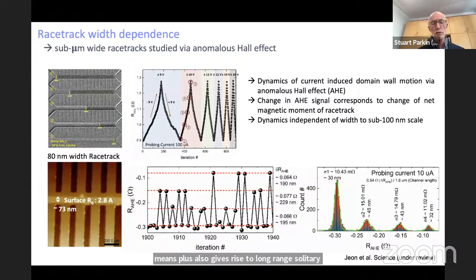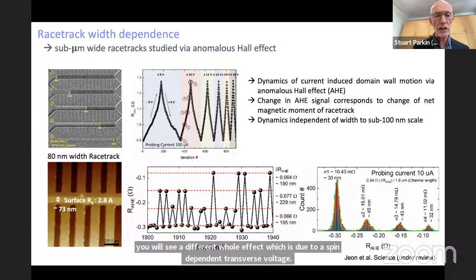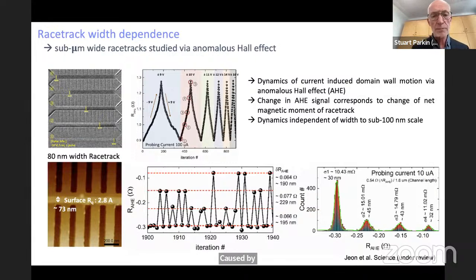But now if we switch to a different technique for measuring the motion of the domain walls, now we look at domain walls where we're detecting them using the anomalous Hall effect. So when you pass a current through a magnetic material, you will see a different Hall effect, which is due to a spin-dependent transverse voltage caused by spin-dependent scattering of the electrons from the magnetic moments, typically.